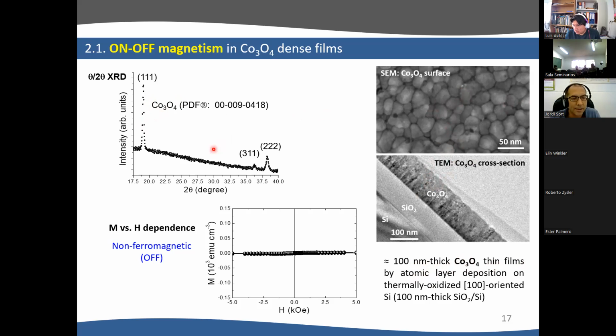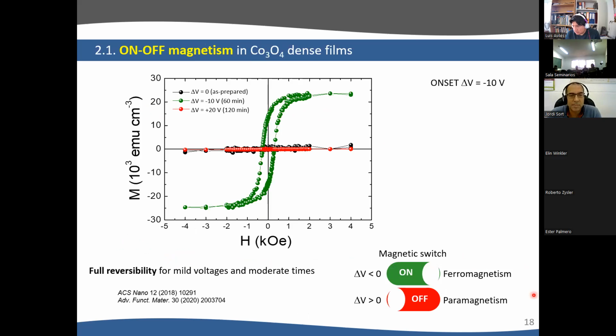And you can see here that they have some texture and that the M versus H dependence at room temperature is paramagnetic. We don't have any magnetic signal, as expected. And now here is what happens when we apply minus 10 volt for 1 hour. We start from a paramagnetic response, the black curve here. We apply minus 10 volt for 1 hour and you can see that, well, not suddenly, in 1 hour actually, you generate a ferromagnetic response.